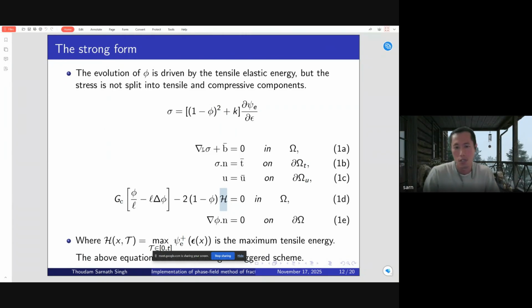This H drives the phase field evolution equation, and now we have a coupled system. One is the force equilibrium equation, and the second one is this one. So we have to solve these two equations. And how do we solve these two equations? We use a method called the staggered scheme. In the staggered scheme, first we solve this equation. We get U, the displacement, from which we get the strain. Once we have the strain, we can get the local strain energy. The local strain energy is passed to this equation, which is the H, and this drives the evolution of the phase field phi. From this we get phi, and we use this phi in the force equilibrium equation.